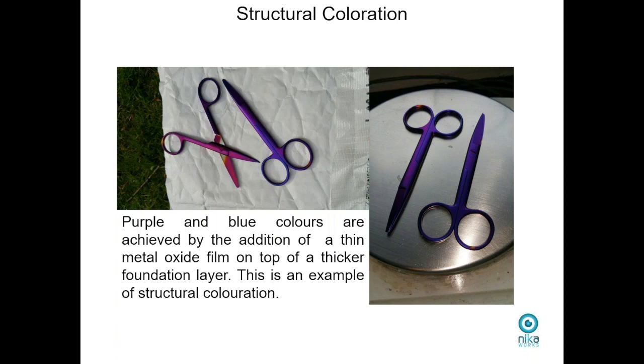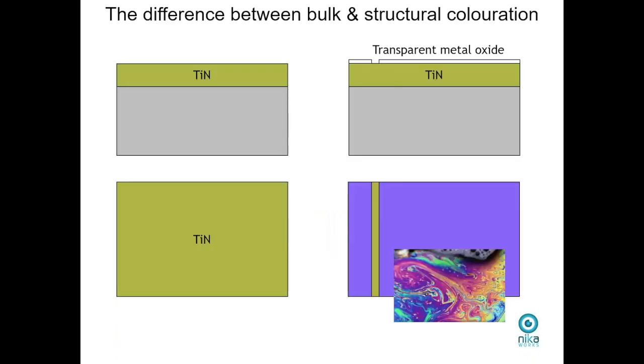Now, I'm going to begin to move us now from truly thin film coatings, and I'm going to begin to nanostructure them. So this is moving into the 2D, and we'll move into the 3D. To achieve the coloration here, what we've done is we've deposited titanium nitride, which, as we've learned, is a gold color. And then what we've done is we've deposited on that titanium nitride a very thin layer of titanium dioxide. Titanium dioxide is transparent. So what we've done, in fact, is a little bit like, if you look at the bottom right-hand side, you'll see something that looks like an oil film on water, and that's exactly what we've done.